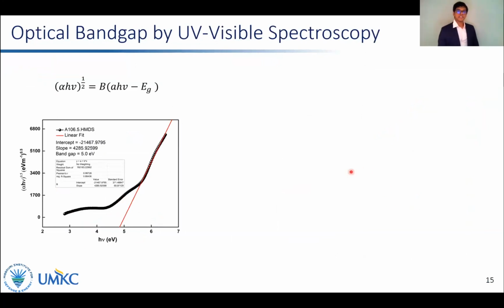Optical band gap for these films was determined from ultraviolet visible spectroscopy. The absorption coefficient data was plotted against photon energy using a Tauc relation for disordered materials. According to the Tauc relation, the x-intercept of this slope gives us the band gap for these films.